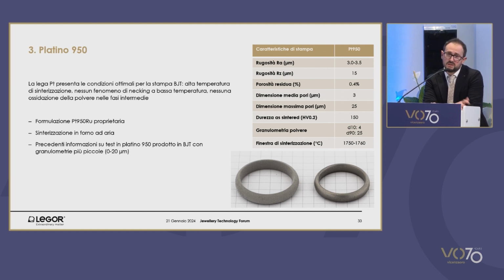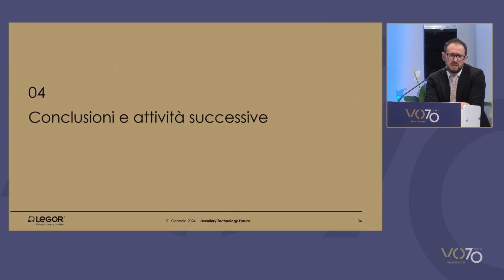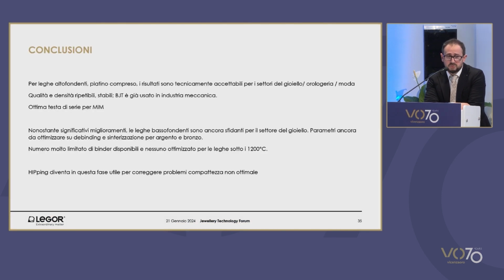So from the very first printing experiment, we achieved a residual porosity less than 0.5%. So dense items have been obtained with a powder that was slightly coarser than described in the literature, which had 20 micron. So we can actually think about using this powder also to produce products to be sold on the market.